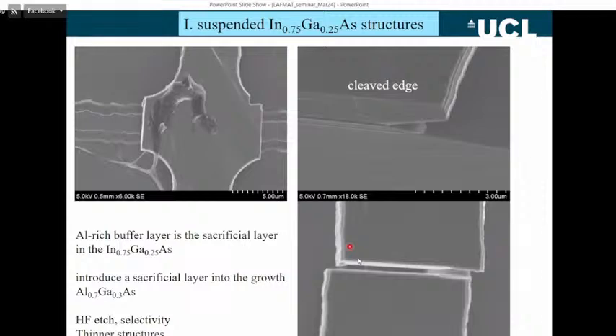You can see in the image here, it's a freestanding channel, but the channel is just cracked. Also, likewise, we can see here a cross section through the channel where we've cleaved, and you can see how the etch can etch away underneath to make the free suspended layer. The image on the top left here was a device that had failed, and you can see where the device had lifted off from the substrate, but had then sheared away and cracked. So it was a very useful study to do, to find out how thin we could make these layers. In fact, it turns out these layers are strained, so there's an inbuilt strain into the layers, and the strain stops them collapsing.